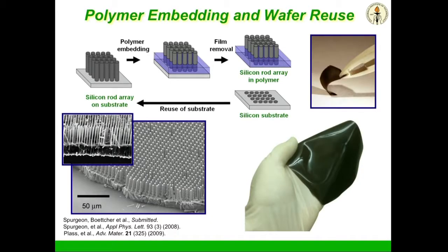Another important point is not only is this really cheap silicon, but there's no waste. There's no kerf losses. When you grow a crystal of silicon to make a big boule, the first thing you do is have to saw it up, and the thickness of the saw blades is such that you lose half of that precious silicon in the first place that can't be recycled. We have no kerf losses because everything that we grow is peeled and fully embedded into our material, and then we grow again and peel again. We use 1% of the silicon that you would use in a standard wafer to get the same absorption with the same potential efficiency from really cheap precursors with no processing, and flexibility that you can roll the stuff up and unroll it to deploy it.